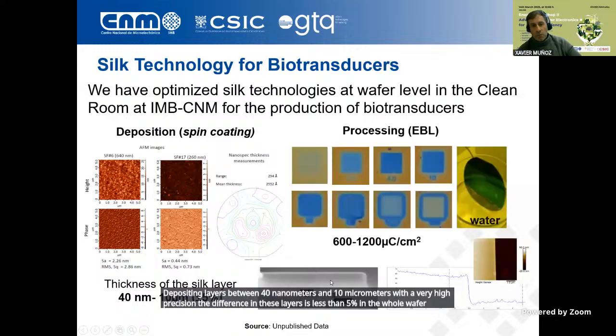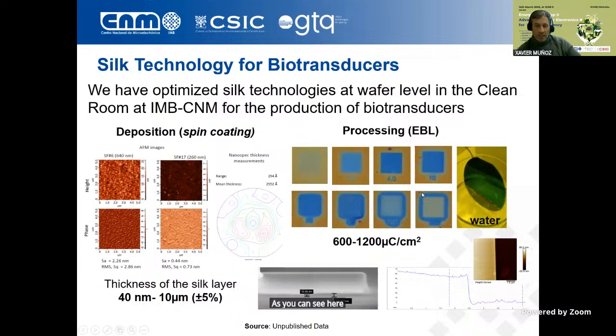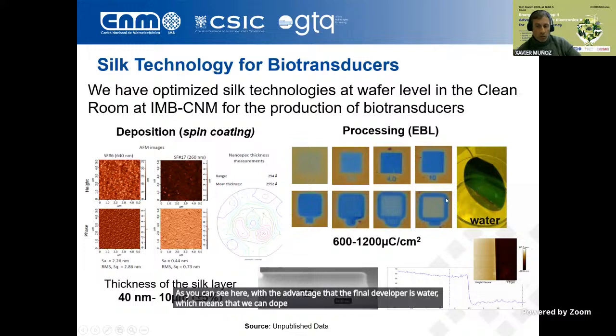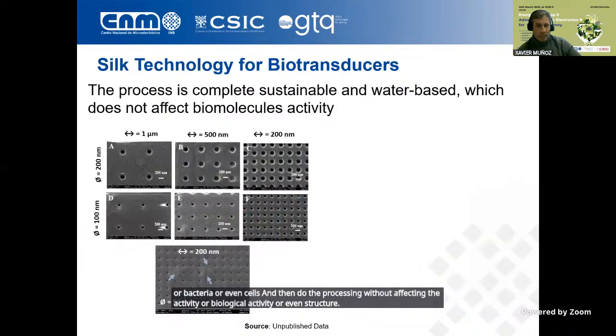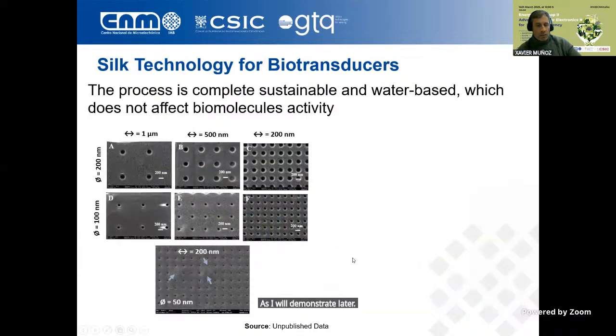And we also optimized the processing of these silk fibroin layers with EBL, as you can see here, with the advantage that the final developer is water, which means that we can dope these layers with biomolecules, for example, enzymes or bacteria or even cells, and then do the processing without affecting the activity or biological activity or even structure, as I will demonstrate later.